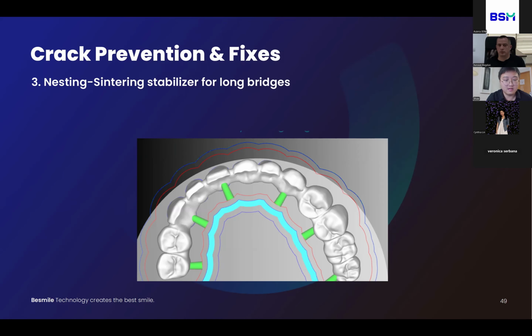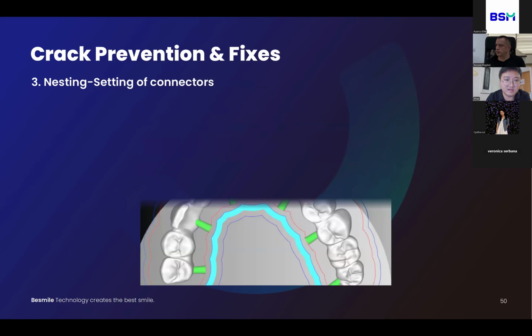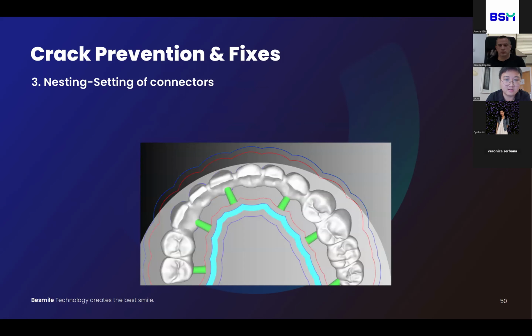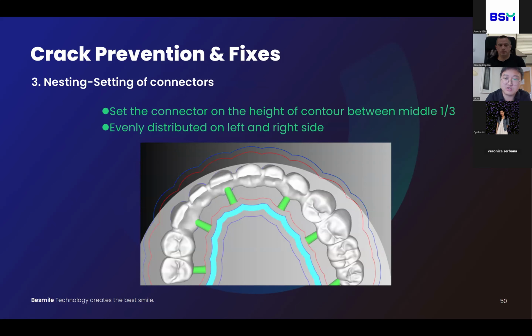And as for the position of the connectors, we recommend to set the connectors on the height of the contour, between the middle one-third area. And set 6 to 8 connectors evenly distributed on the left and right side.